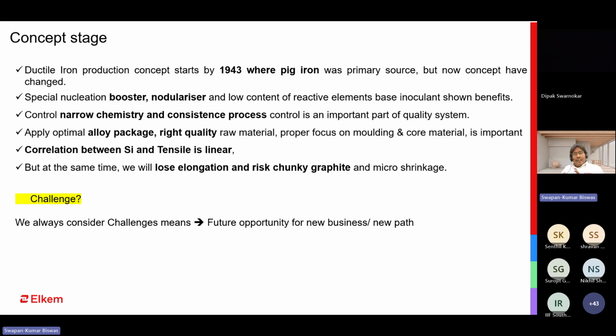So in ductile iron or gray iron, you always need to focus on the nucleation booster. That is primary, from the liquid metal. Whatever casting process you are applying, first you have to think about when the metal is ready, what is the nucleation level. Gray and ductile iron are both the same when the metal is inside the furnace, but after magnesium treatment, that metal converts into ductile iron.